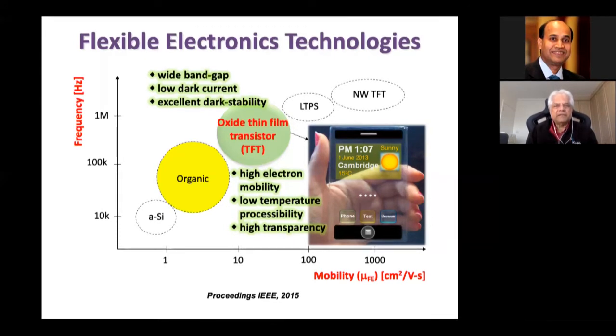Because it's a relatively new material, perhaps 30 years old, essentially. And what you really want, for me, as far as designing a good sensor interface is concerned, is a very wide band gap. A wide band gap means a low thermalization current. So if you look at silicon, it's 1.1 electron volts. It has a higher thermalization current than, for example, gallium arsenide, which is 1.45 electron volts. And that low dark current is extremely important because that sets the noise limit for the sensory signal you're trying to read.